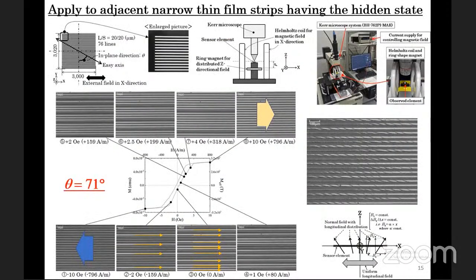Now let me introduce the case of multiple elements. This sheet shows an experimental result for adjacent elements having the hidden state. The 20 micrometers width and 3000 micrometers length elements were adjacently aligned with the line space as 20 micrometers. The result shows that the elements in the adjacent layout still have the same property as a single element having the hidden state.